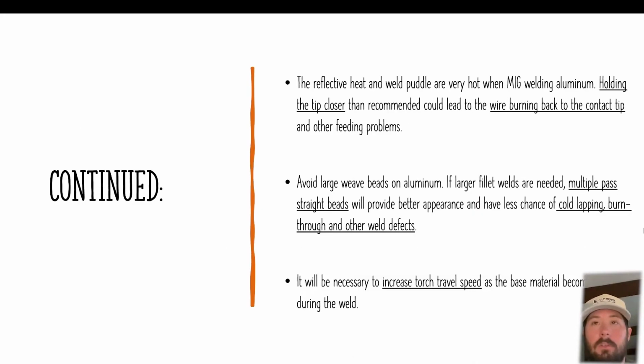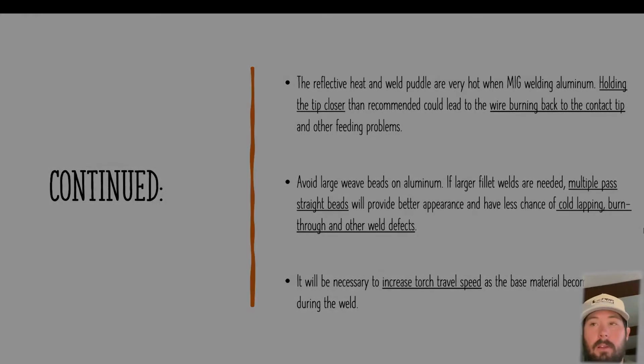And that's mostly due to it being very hot when welding aluminum, so if your contact tip is too close, it could lead to the wire burning back, or you could run into feeding problems. With aluminum, you want to avoid large weave beads. If you need a larger fillet, weld it in multiple passes.